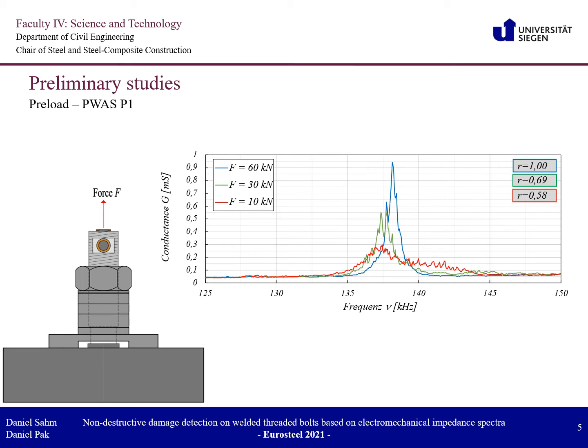Next, I would like to show you the results of the preload test. For the preload test, a hexagon nut was clamped via a spherical leveling washer against the load cell, which was fixed between the base plate and the nut to apply a bolt preload force. You can see it right here. In the diagram, you can see the conductance spectrum for the preload stages 10 kN, 30 kN, and 60 kN. The evaluation of the measured conductance spectra showed that different stages of preload result in a significant change of the electromechanical impedance spectra in the range between 135 and 150 kHz.